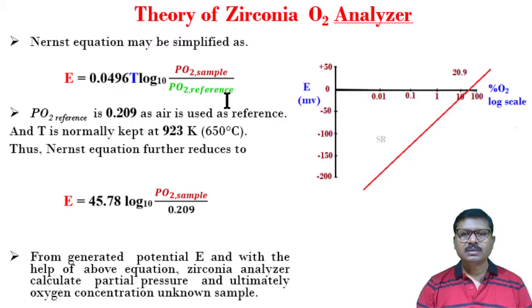Now normally for analysis of oxygen, normal air is used as the reference. So the partial pressure of oxygen in air is 0.209, and at the time of analysis the temperature is normally kept at 923 Kelvin, which is equivalent to 650 degrees centigrade. So if we put the value of T as 923 and the partial pressure of oxygen as 0.209, then this Nernst equation will be simplified again as E is equal to 45.78 log of the partial pressure of oxygen in the sample divided by 0.209. So this is the simplified equation.